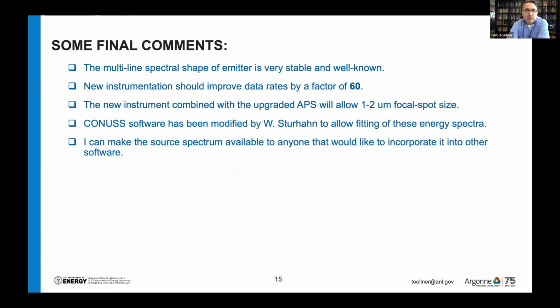And so I just have some summing up here. The multi-line spectral shape of the emitter is very stable and very well known and produces very high counting rates. And so we're confident that this is the best approach available to us. The new instrument will introduce a 1-micron focusing, so we'll do Mössbauer microbeam with a much smaller spot size. And the CONUSS software has already been modified to handle this kind of data. I can make the source spectrum available to anyone else who would like to incorporate this kind of fitting into any other software.